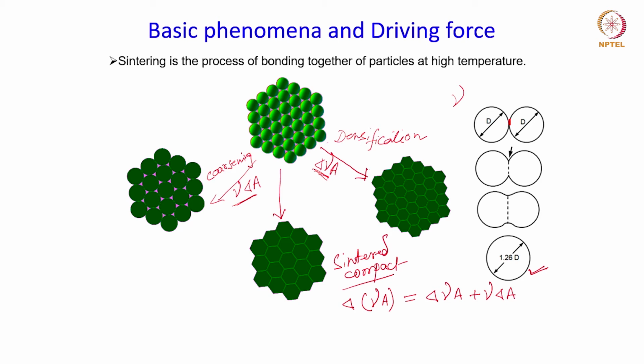Right? So these phenomena that take place during the sintering process basically lead to a decrease in the total surface energy of the system, and that is what drives the process. Okay. So therefore we can say that the driving force for the sintering process is the reduction in total surface energy. Okay.